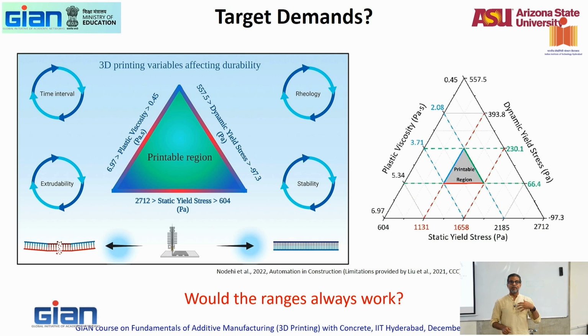Or you say that maybe my sand content is not enough. I may have to increase the sand because sand comes with some stiffness already. So increasing the sand content automatically increases the stiffness of your mix, right? But increasing the sand might play around with your extrudability. So again, the point is that there is no one size fits all solution here. You have to understand the lay of the land, understand what these basic parameters are, and build up your understanding based on that and be able to do it.